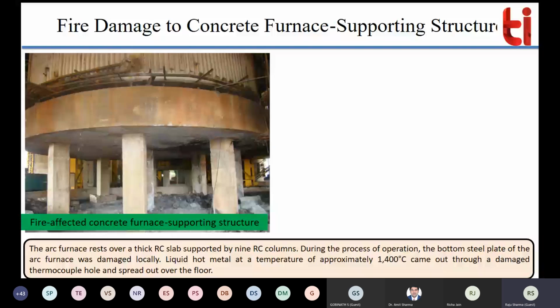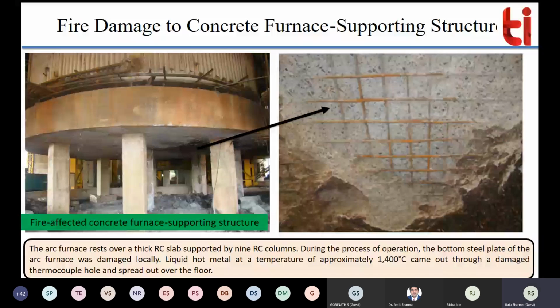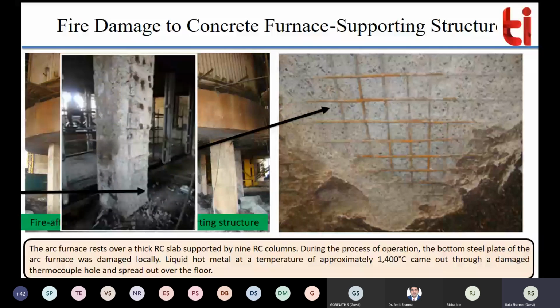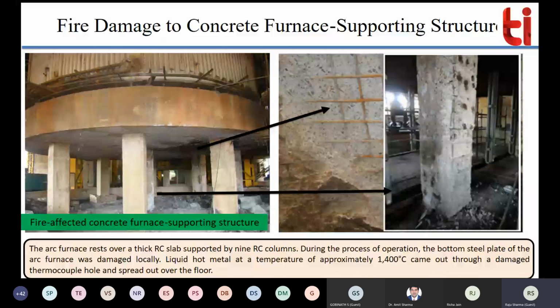When the failure happened, the team analyzed this particular structure and found that there was degradation in the slab because of that high temperature. During the process of operation, the bottom steel plate of the arc furnace was damaged locally. From some point the damage occurred, and through that damage the liquid hot metal, which was approximately at 1400 degrees Celsius, interacted with the concrete top surface, and that temperature is not appropriate for the concrete. They studied this and found that spalling of the cover has happened on the bottom side of the slab. They also looked at the column and found that degradation has happened in the column face also, right?